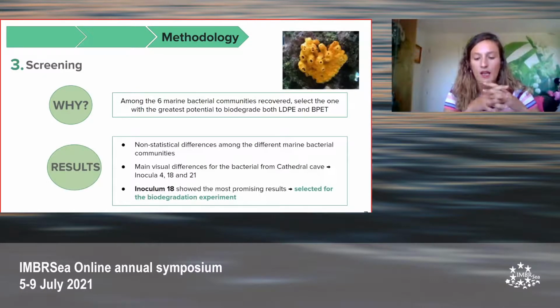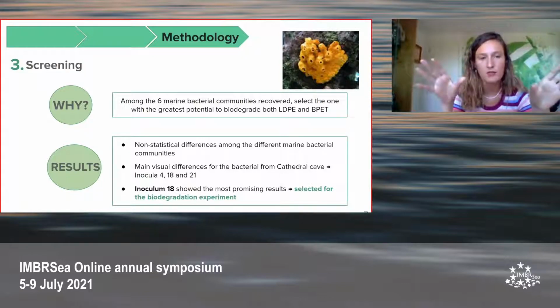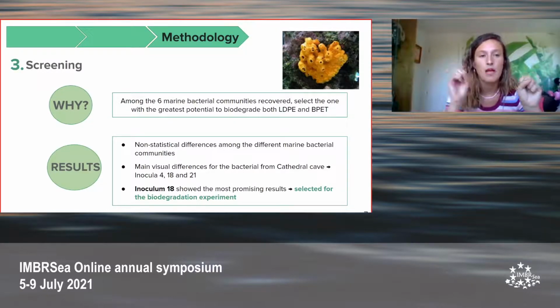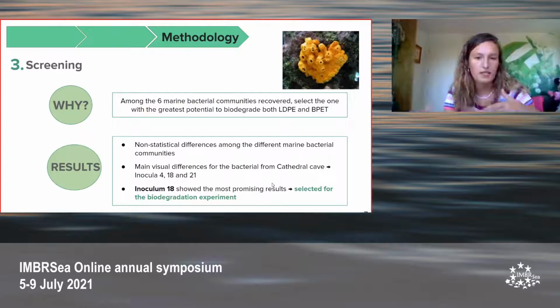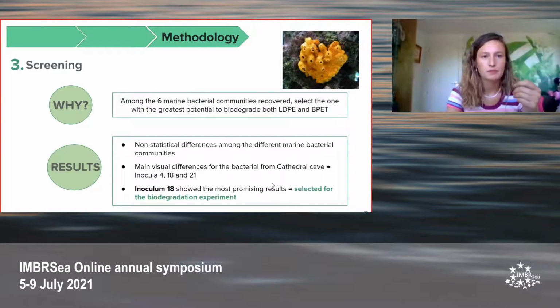But what did we obtain? Well, we didn't see statistical differences among the 6 bacterial communities, but visually we could see that the highest potential and the main differences were obtained in the samples recovered from the Cathedral Cave, which are the inocula number 4, 18, and 21. And among these 3, the inoculum 18 showed the most promising results and was therefore selected for the biodegradation experiment.